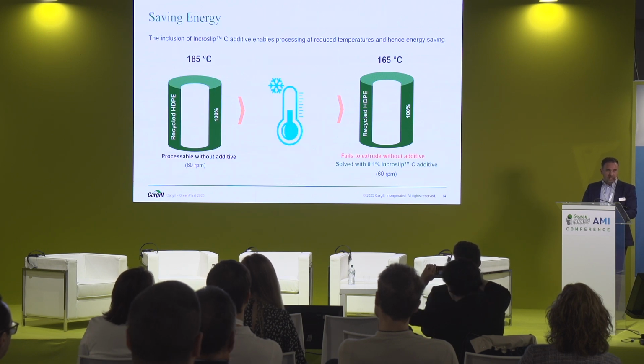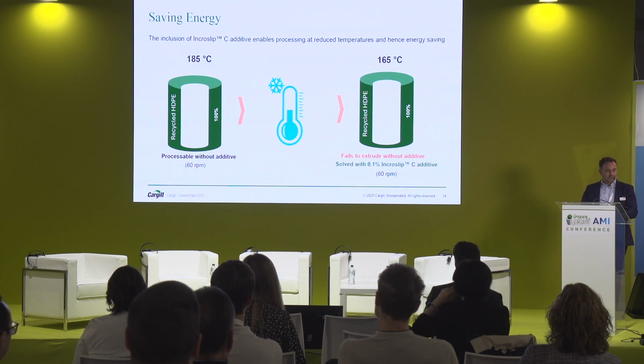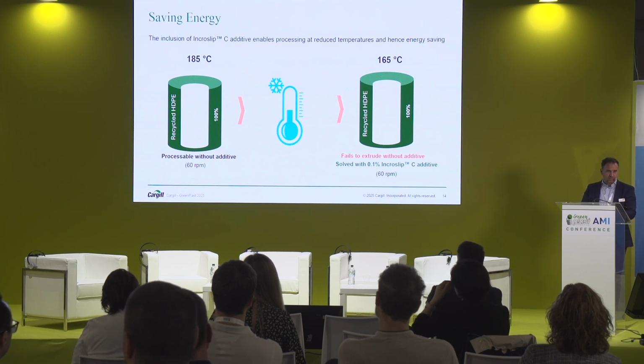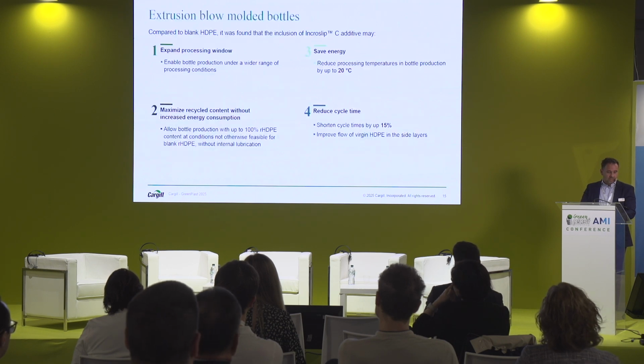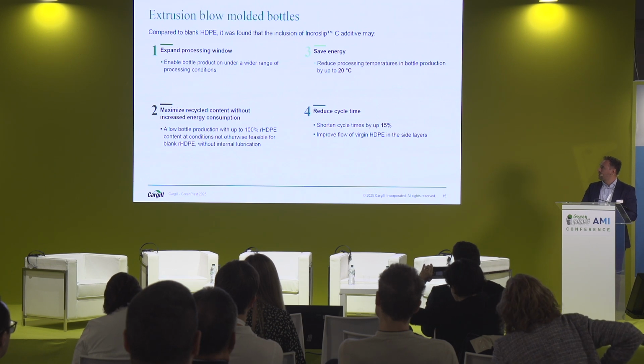And also the energy savings and less degradation to the polymer that can be achieved by using the additive and enabling the reduction of the processing temperature, in this case by an impressive 20 degrees Celsius. So these results were nice and clear. And here is the summary with all the highlights of this study.